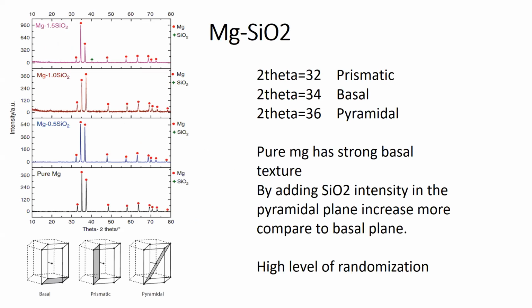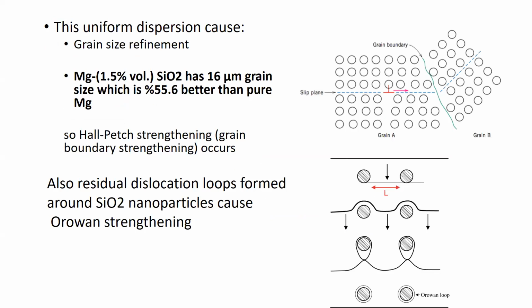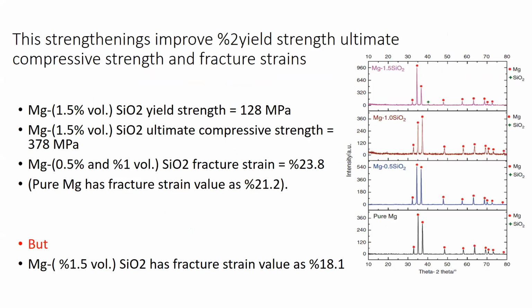X-ray diffraction shows strong basal texture in pure magnesium, but by adding silicon dioxide, intensity in the pyramidal plane increases. These results show that nanoparticles are dispersed in the magnesium more randomly. This uniform dispersion causes grain size refinement and so Hall-Petch strengthening. Also, since residual dislocation loops form around silicon dioxide nanoparticles, Orowan strengthening occurs. This strengthening improves yield strength, ultimate compressive strength, and fracture strain.